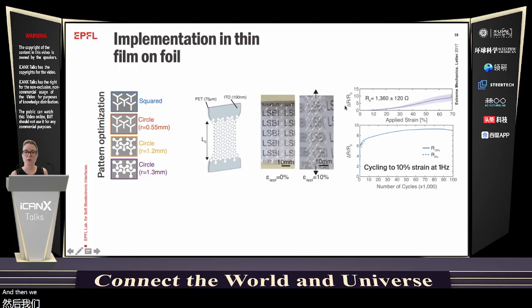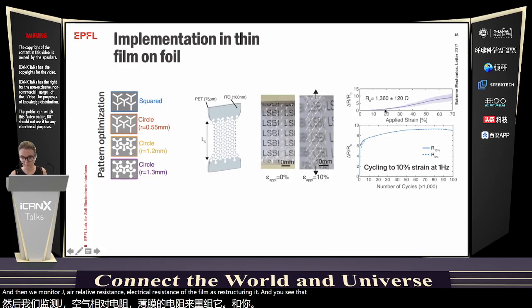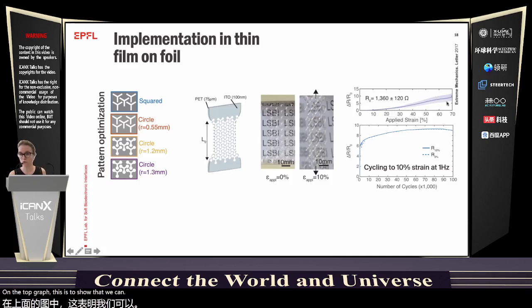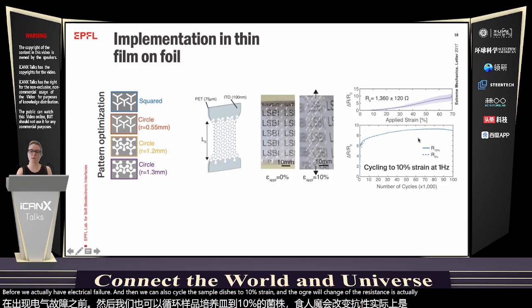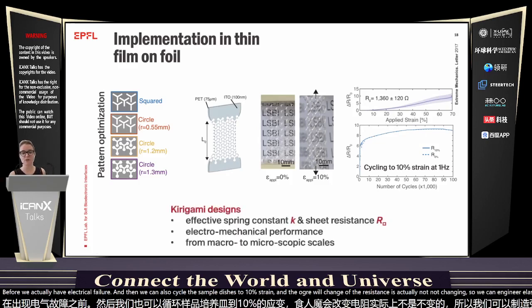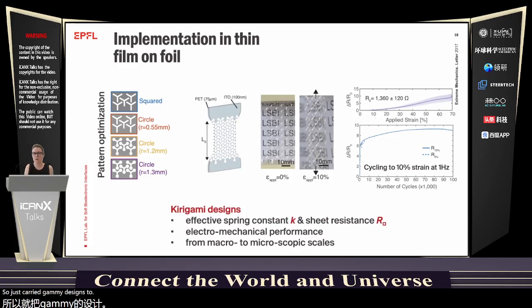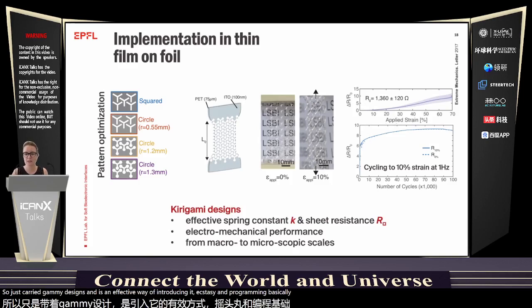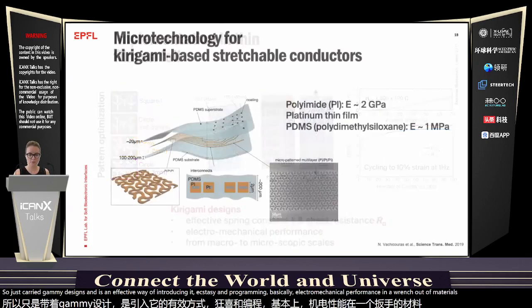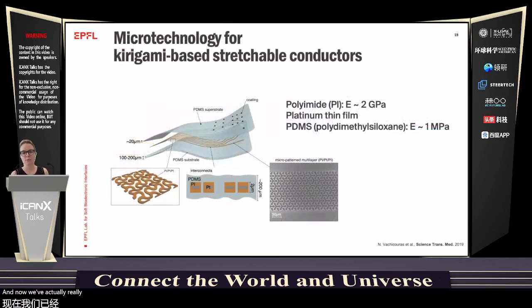And then we monitor the relative electrical resistance of the film as we're stretching it. And you see on the top graph that we can stretch very far before we actually have electrical failure. And then we can also cycle the sample. This is to 10% strain. And the overall change of the resistance is actually not changing. So we can engineer elasticity into ITO. So these Kirigami designs are an effective way of introducing elasticity and programming basically electromechanical performance in a range of materials.